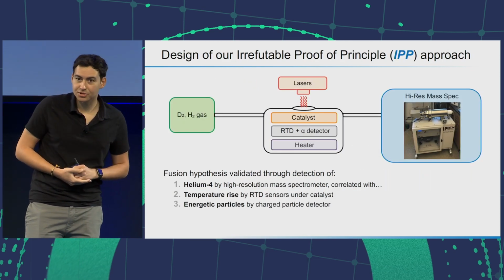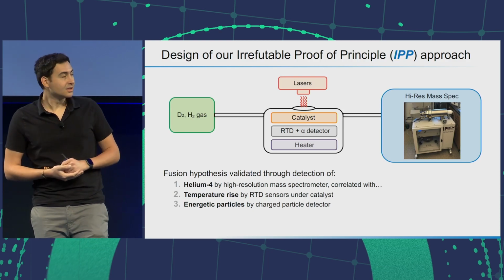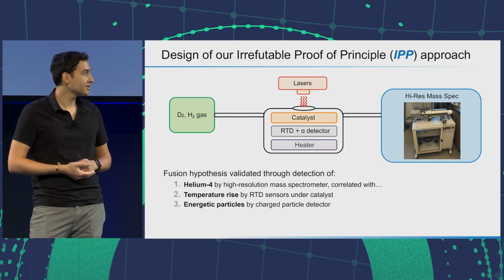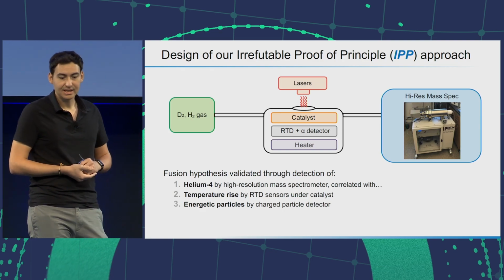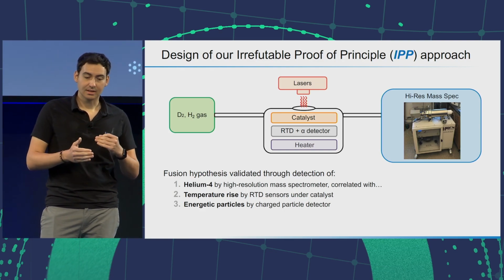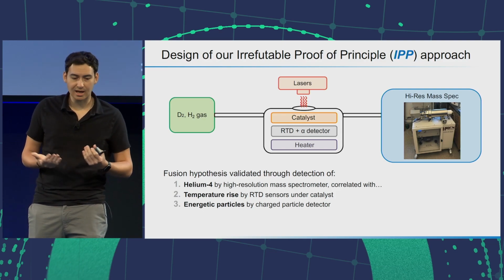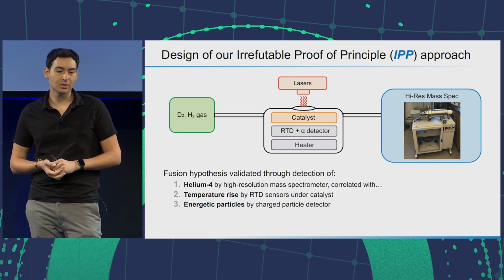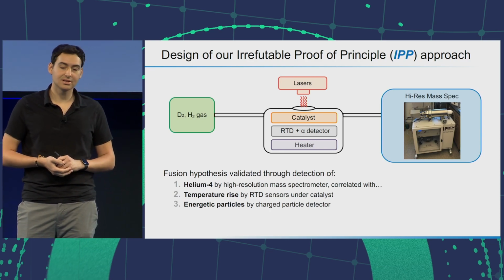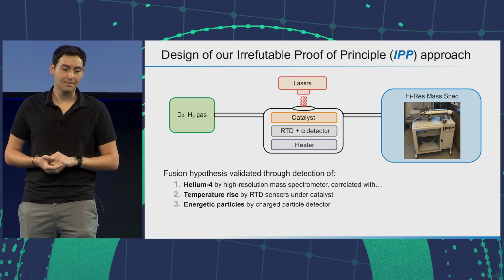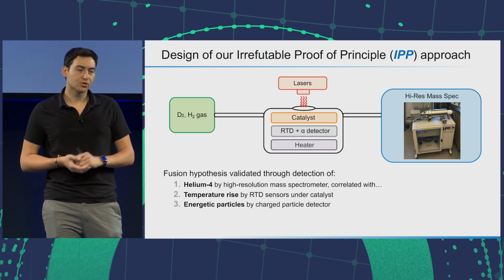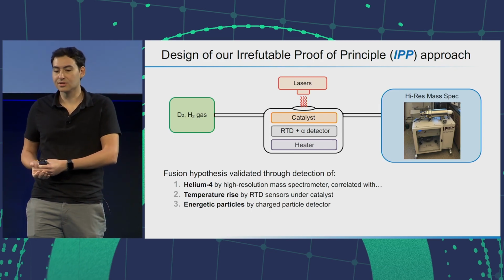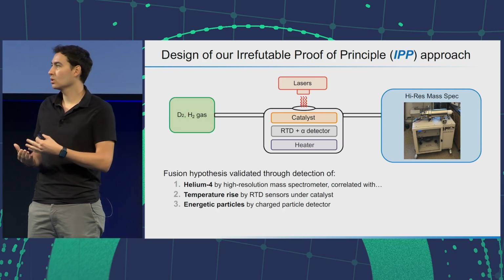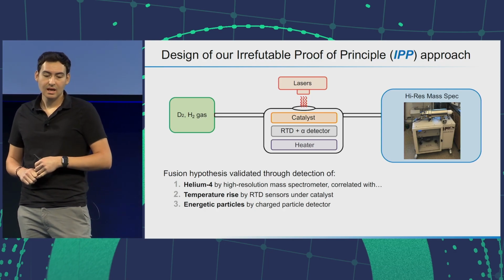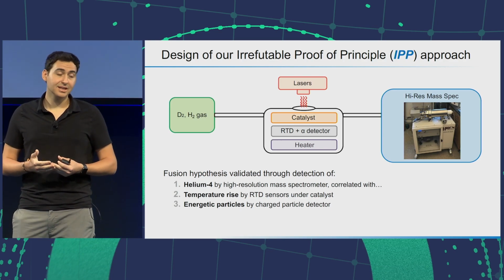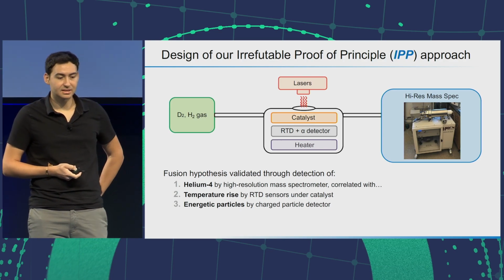So here's a little cartoon of what our IPP approach looks like. We have deuterium or hydrogen gas flowing into our reactor. We have a window where we zap it with the lasers. We have our catalyst layer and some detectors in there measuring temperature and even high energy charged particles. We can control the temperature with heat, and then downstream of the reactor we have a high resolution mass spec. So this is our crown jewel in the lab. And as it says on the bottom, we're trying to validate this hypothesis with these three detectors. So focused on helium, number one, but also correlating it with these other indicators, so temperature rise, and then energetic particles, which would be indicative of a nuclear reaction, especially in the MeV scale.